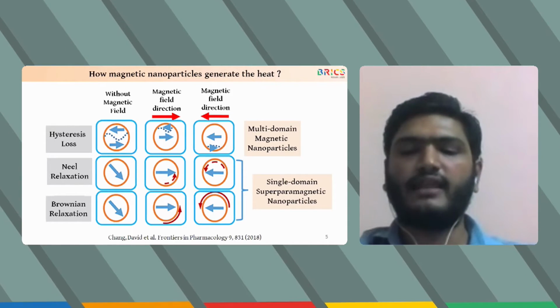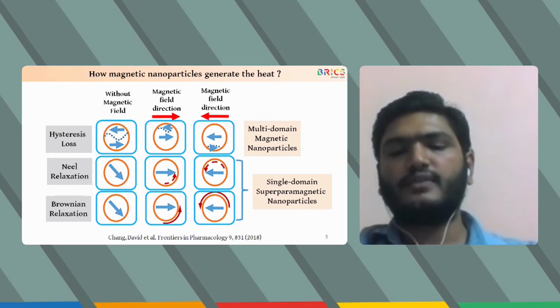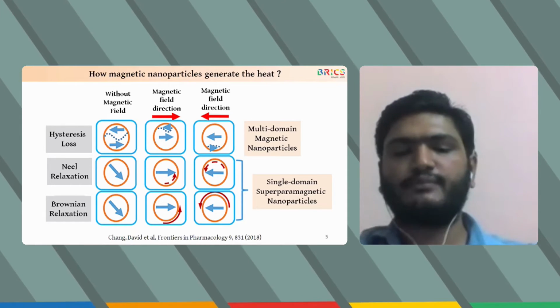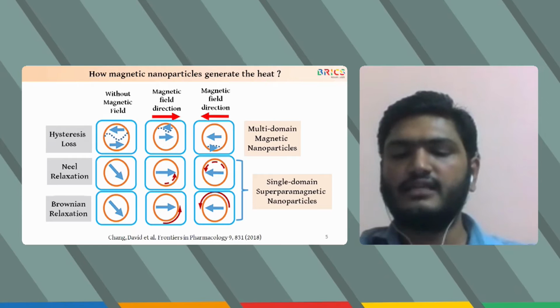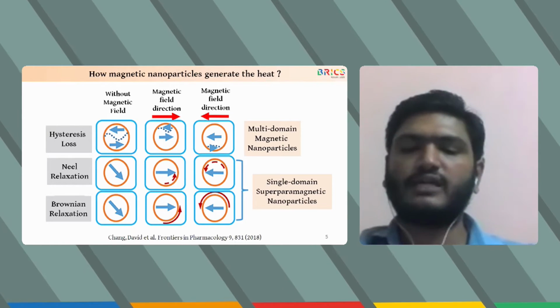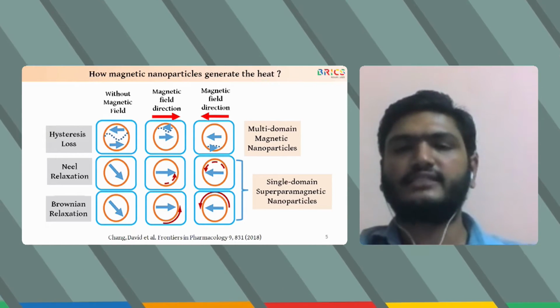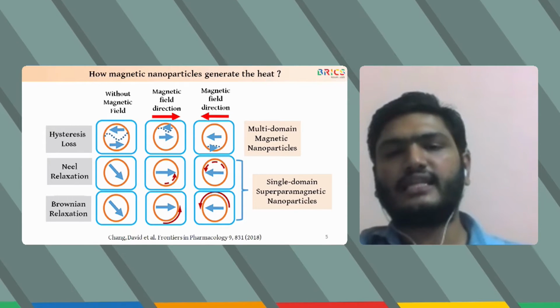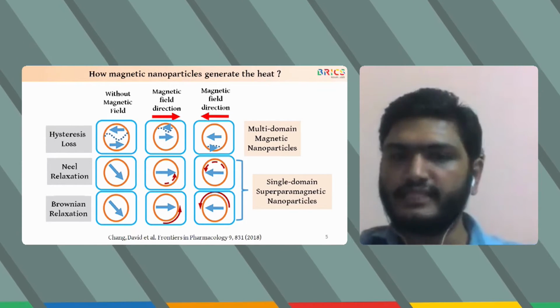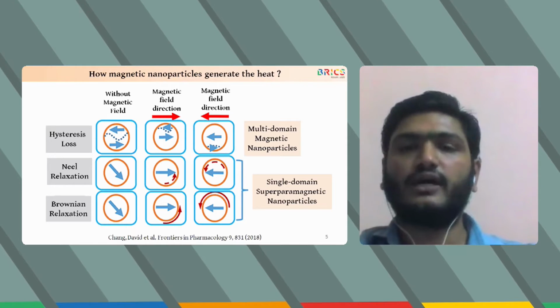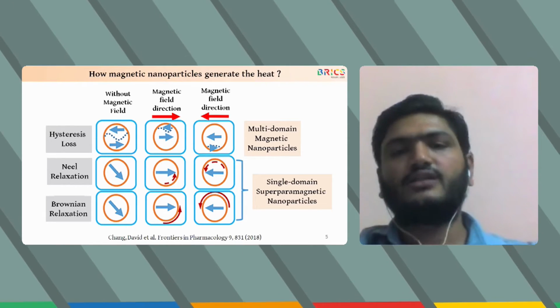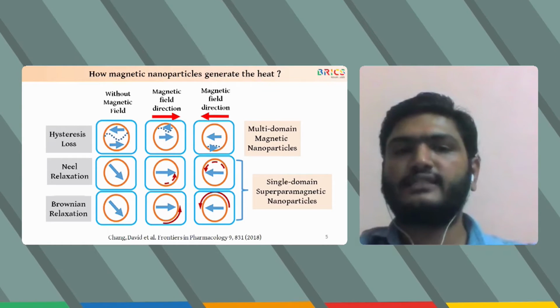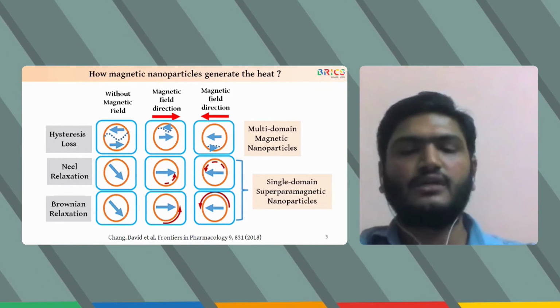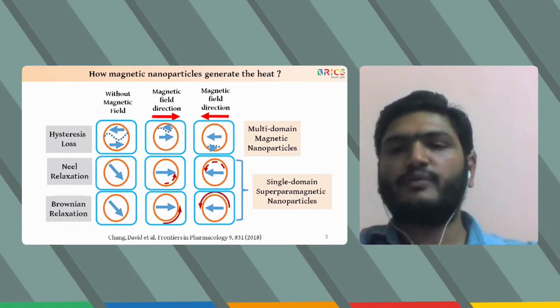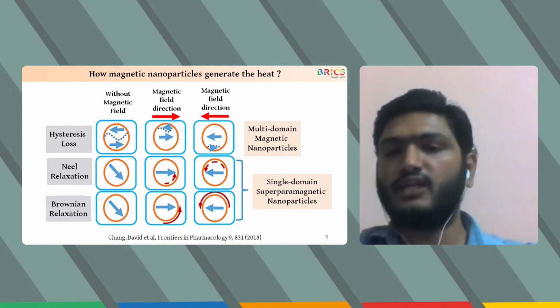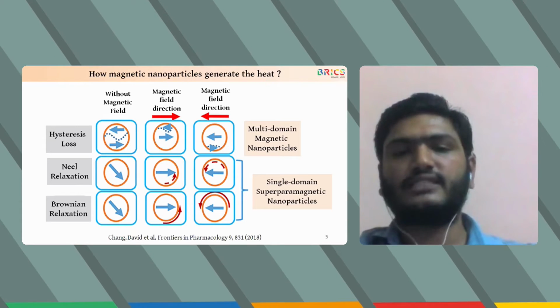Hysteresis losses may be determined in a well-known manner by integrating the area of hysteresis loops, which is a measure of energy dissipated per cycle of magnetization reversal. Thus, the total heating is proportional to the frequency of the applied field and the area of the magnetic hysteresis loop. In Néel relaxation, the nanoparticle remains fixed in place, but the magnetic moment reverses direction to align with the external magnetic field. Whereas the Brownian relaxation mechanism is characterized by the rotational Brownian motion of the nanoparticle itself. In the case of multi-domain magnetic nanoparticles, the hysteresis losses are dominant, whereas in single domain nanoparticles, Néel and Brownian relaxations are dominant.